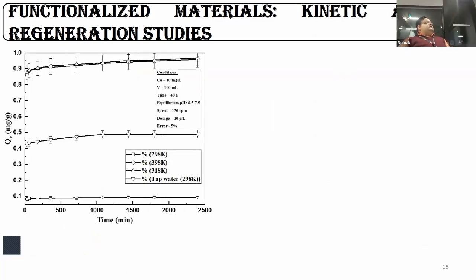We carried out the kinetic and regeneration studies as well. The kinetic studies showed that saturation was obtained somewhere between 1000 minutes, and it was carried out till 2500 minutes. We also included tap water, which had fluoride because we live in a place where fluoride concentration is higher than the WHO limit. We carried out the analysis to see this.